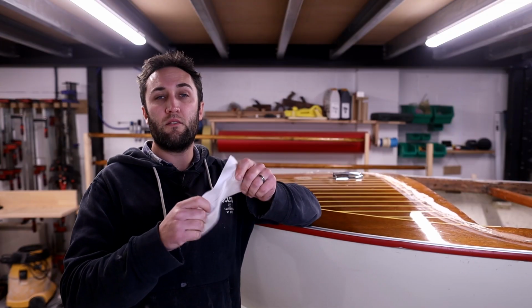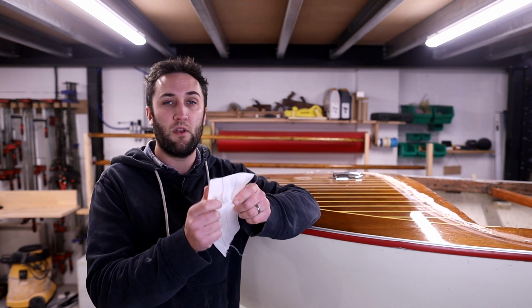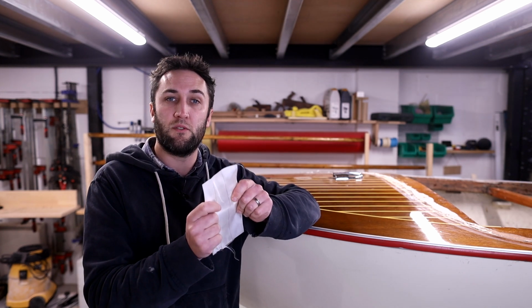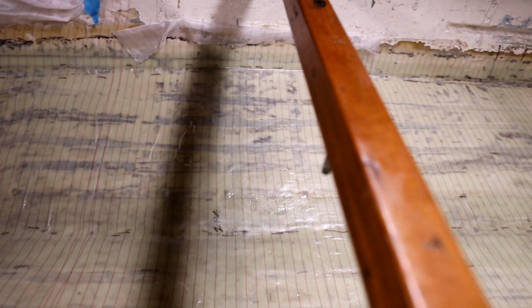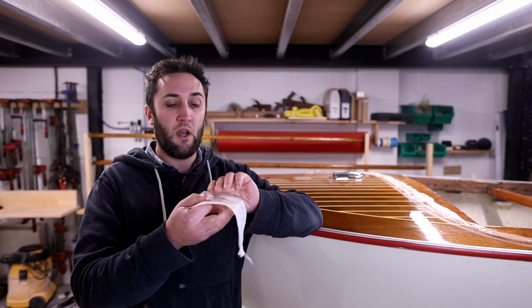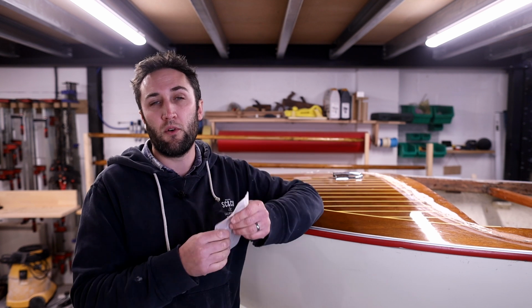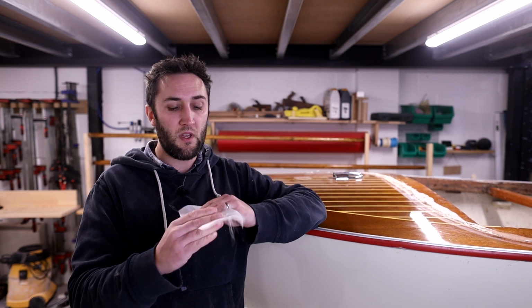It's a thin nylon cloth that is treated with a release agent that the epoxy resin will not stick to. It basically forms a sacrificial layer, so it goes down as the final layer in your assembly, and then you peel it away once the epoxy resin is dried. There are a number of benefits to that. Firstly, it takes away any excess resin that might be in the layup, which will float up to the top and sit on the top side of the peel ply.